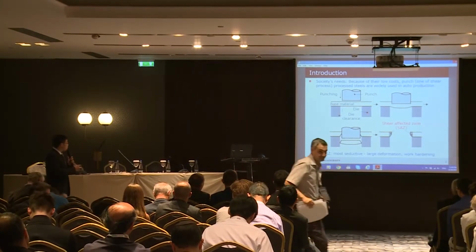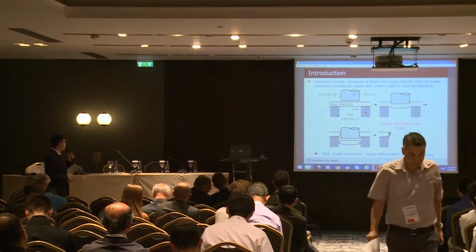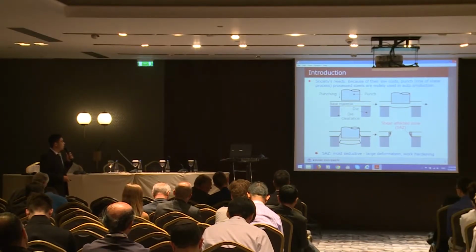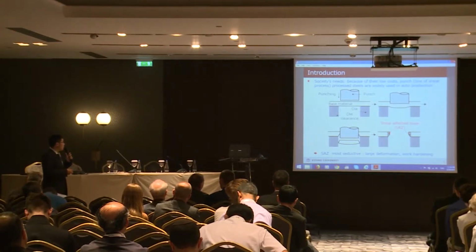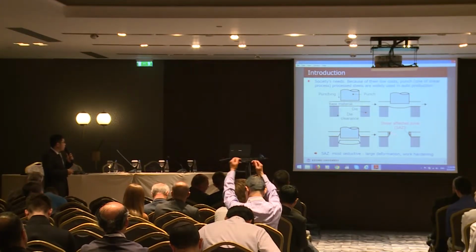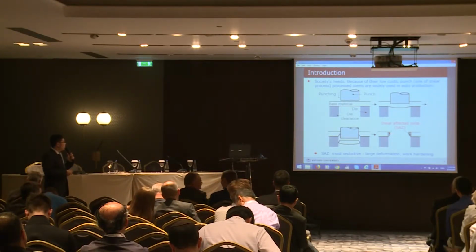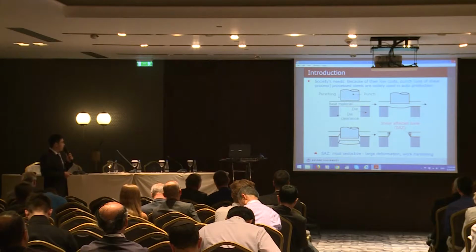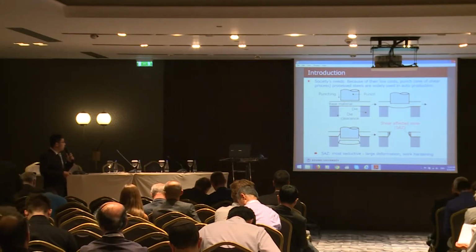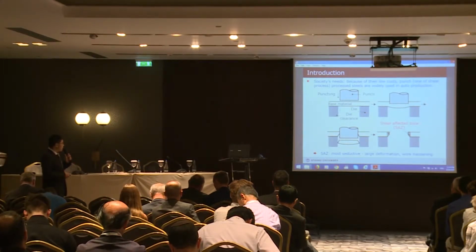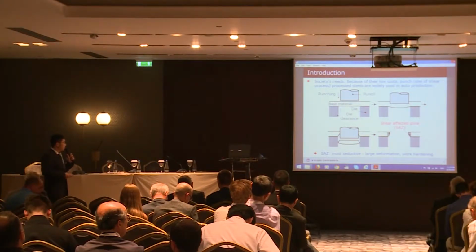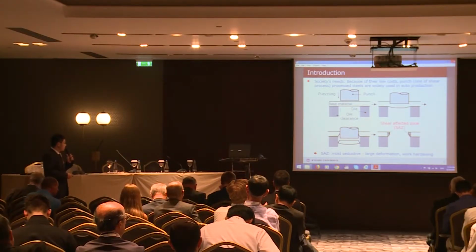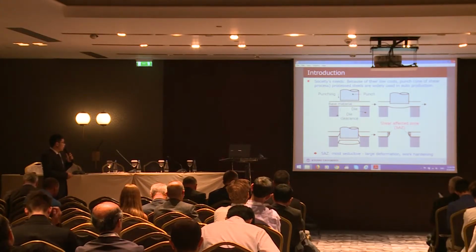Nowadays, because of their low cost, punch processed steel plates are widely used in auto production. Please look at the schema. This is the punched round hole, and in this depth from the hole inner surface, there is a region where the material is affected by the punching process, and the region is called the shear affected zone, SAZ. In the SAZ, the most notable thing is that a large deformation occurs when punching, so that the SAZ has large work hardening.